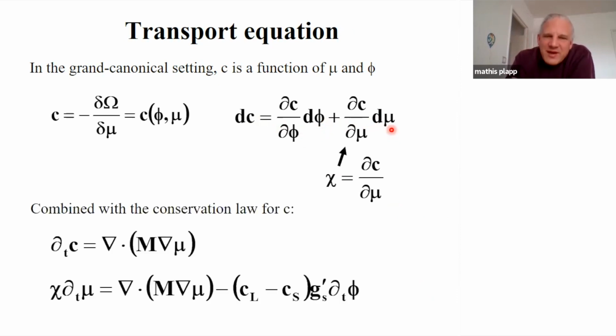And I write down again the equation for the composition. Here's the conservation law that I started from. Now I divide this equation by dt, and I get chi times dt mu. I can express this as dc by dt, for which I use the conservation law, and I make explicit the derivative dc of d phi, which gives me this. And so you see that I have arrived at an equation which is completely equivalent to my temperature equation, but now for the chemical potential.